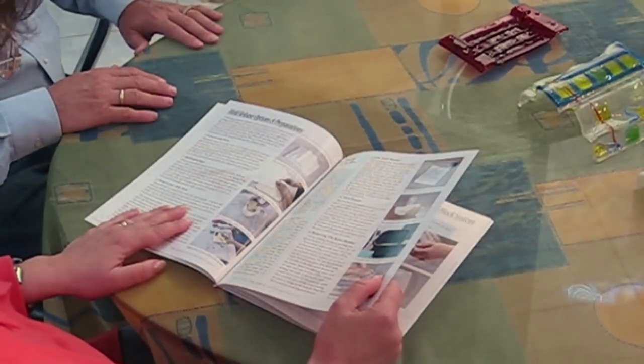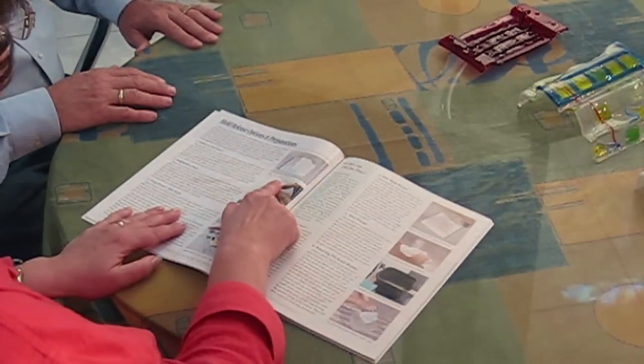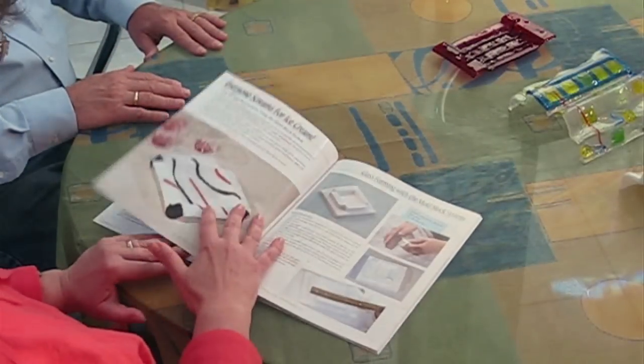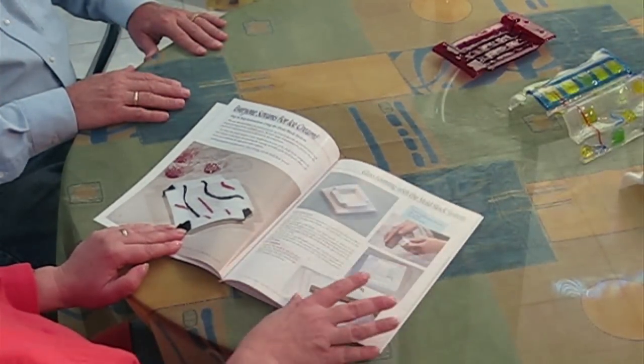At the beginning, we also talk a little bit more about mold release, so that the glass doesn't stick to the board. We have different release options. We have shelf paper or release paper. We have iridescent glass, which does not stick to the Kaiser-Lee board if the iridescent side is towards the board. We have kiln wash, primo primer, kiln wash in a nylon sack, mica powder, and so on. And then we started with the first project, setting up the mold and so on.